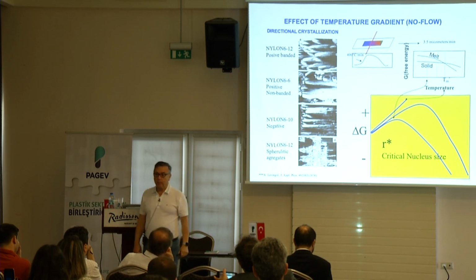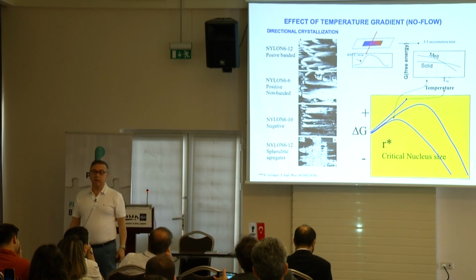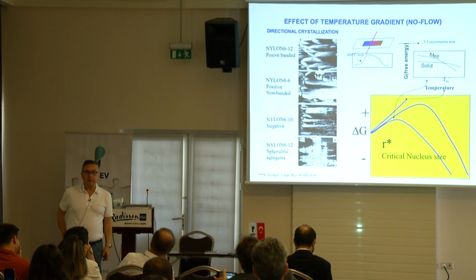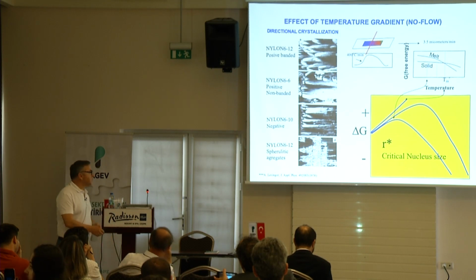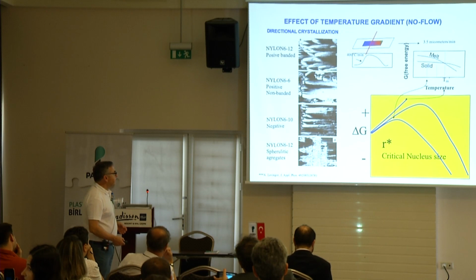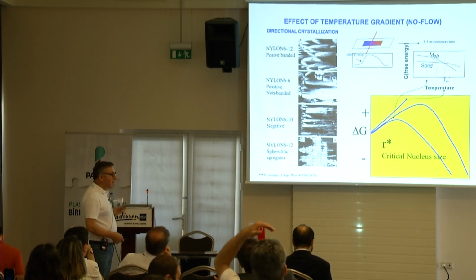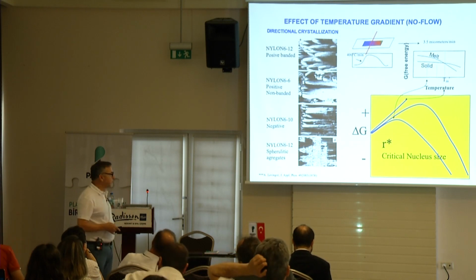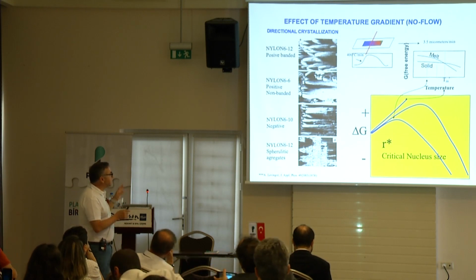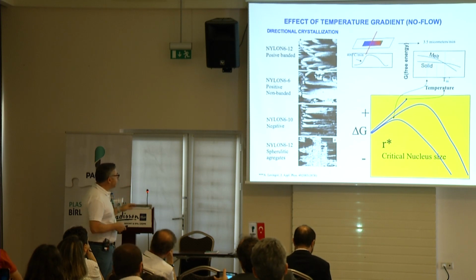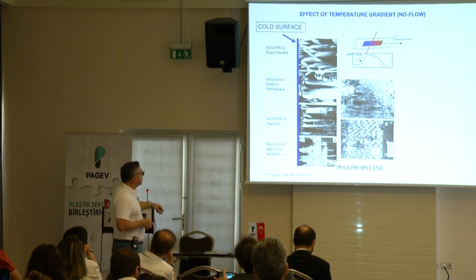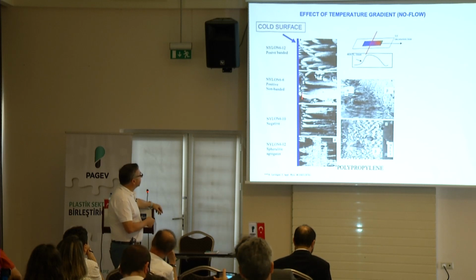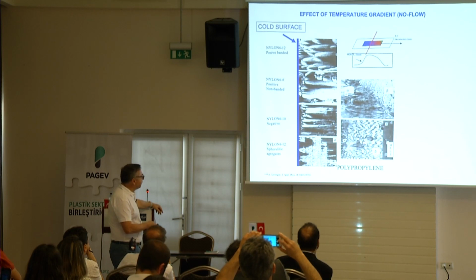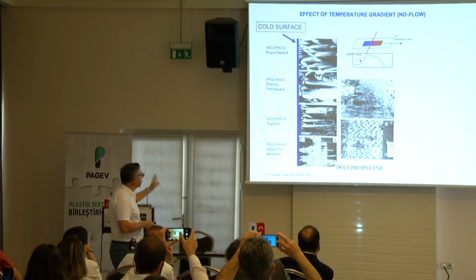This is very common in injection molding, especially fast crystallizing materials. You can actually see that, and I'll show you some examples of it. It's a classic microscopic observation without any effect of flow. Flow doesn't have anything here. Just simply, you heat it up and you cool it down really fast, and then this is what happens. Right? Here are other materials with very similar behavior. Well, lots of details. Some of them grow alpha, beta for nylon and so on. I'm not going to talk about that.